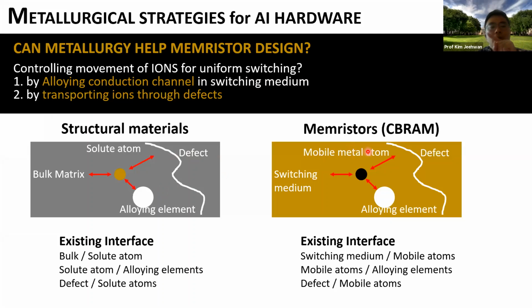Another solution is to have the ion transport through the line defect inside the memristor, okay? Instead of using the amorphous switching medium, we try to use a single crystalline as a switching medium where there is excellent line defect, which is aligned from the top to the bottom, which is called the dislocation. So we try to make some interaction between these mobile atoms with this line defect, which is dislocation, so then we can have the control in ionic movement.